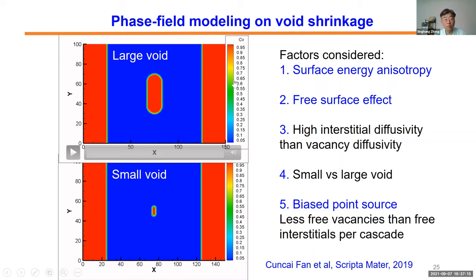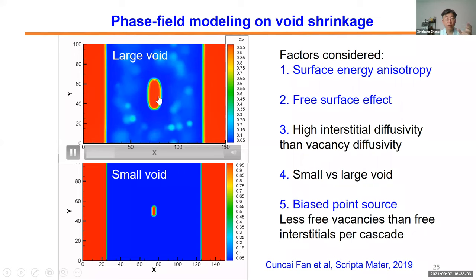So this is the void. This is a vacuum, and the blue here is the interstitial-rich environment. So during phase field simulation, they consider surface energy, free surface, and introduce, basically promote, higher interstitial diffusivities. Interstitials diffuse faster than vacancies. And we were looking at the void size effect, the void shrinkage phenomena. And they also on purpose introduced biased point defects, meaning more interstitials are generated than vacancies. So now if you perform this phase field simulation, all these blue dots are cascade-induced vacancy and interstitial-rich environments. And you find out these larger voids gradually shrink, but the aspect ratio, meaning the length versus the width ratio, didn't change dramatically.